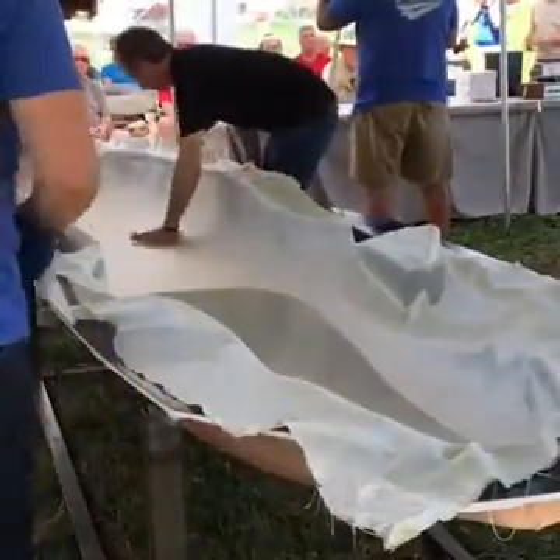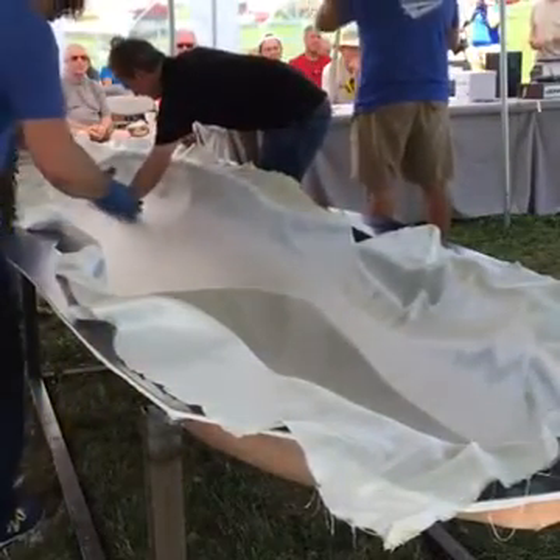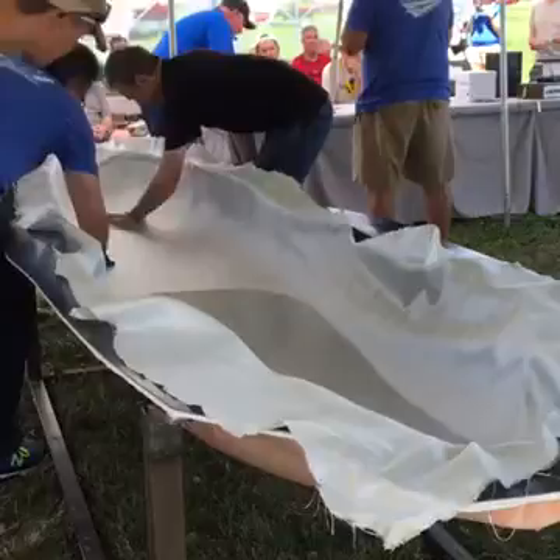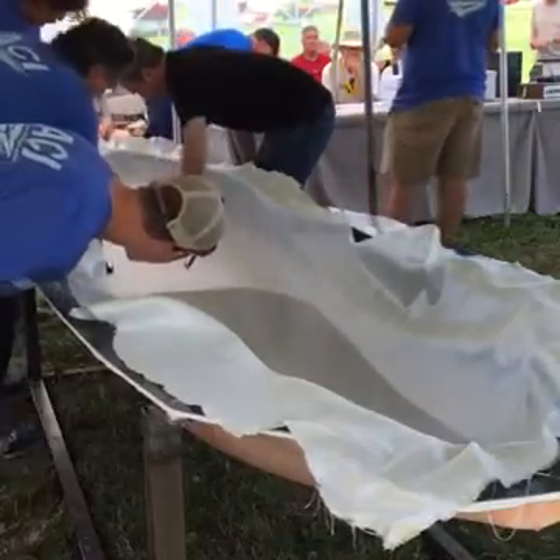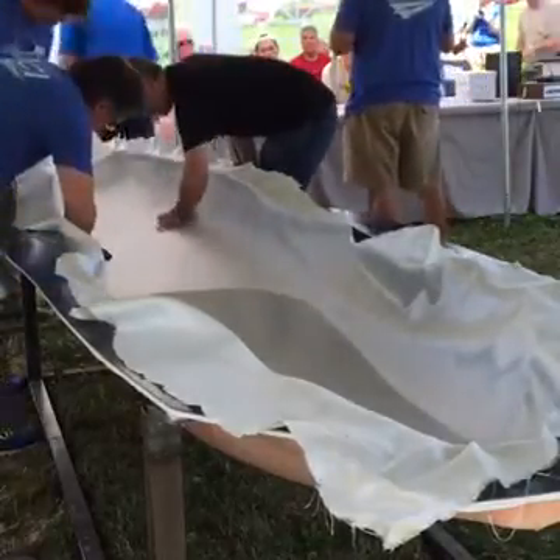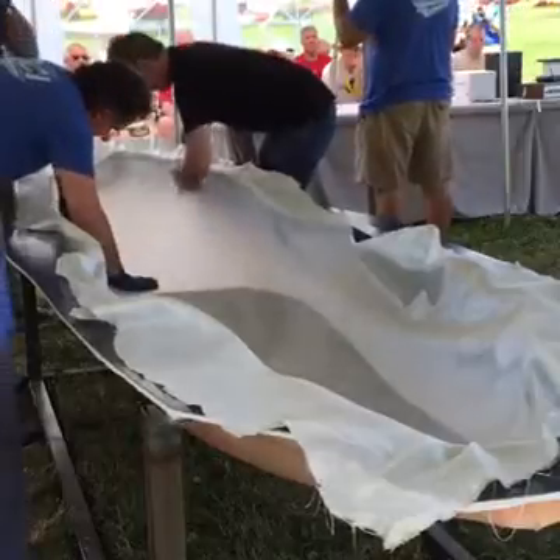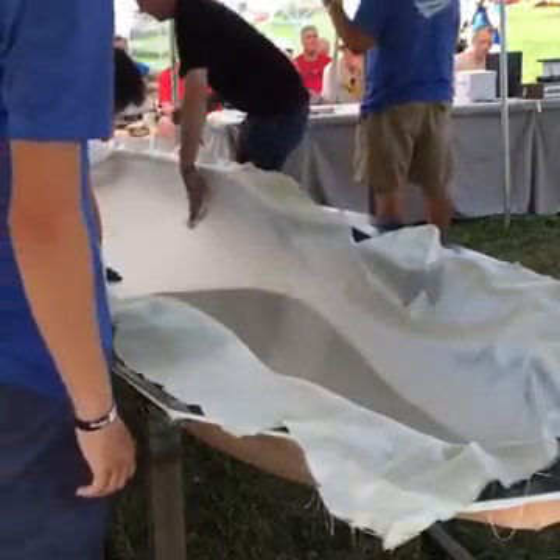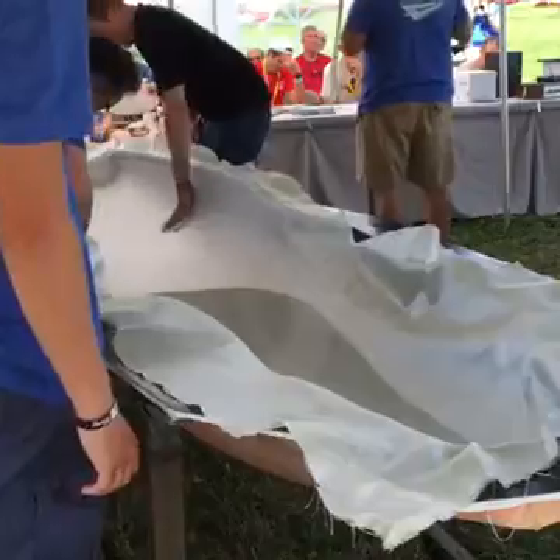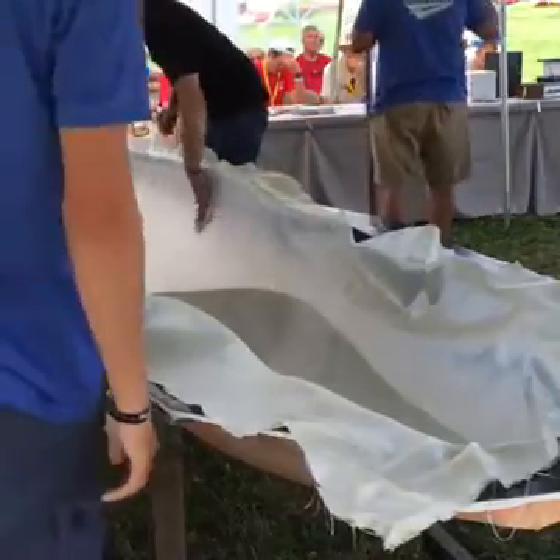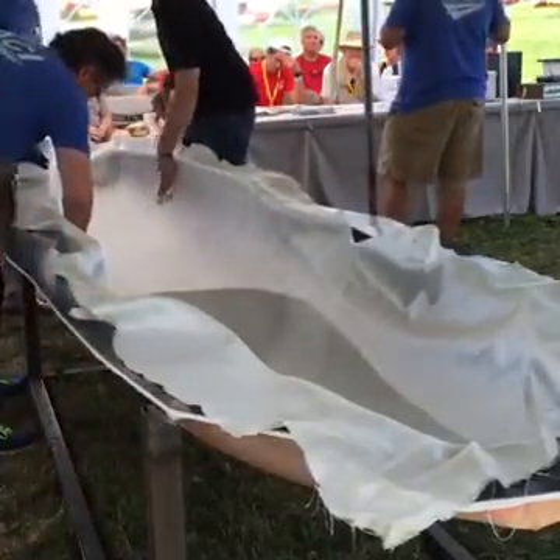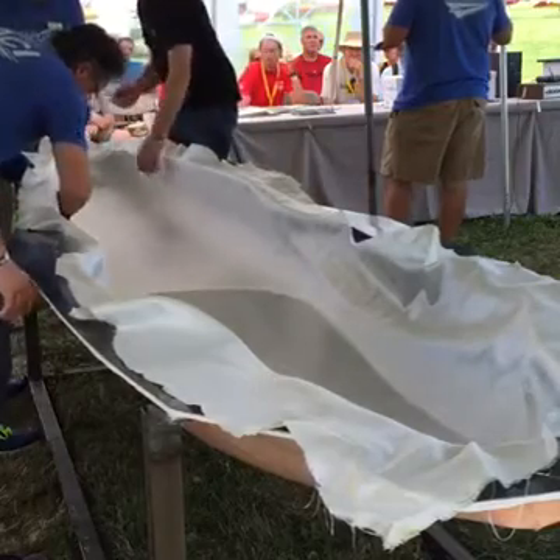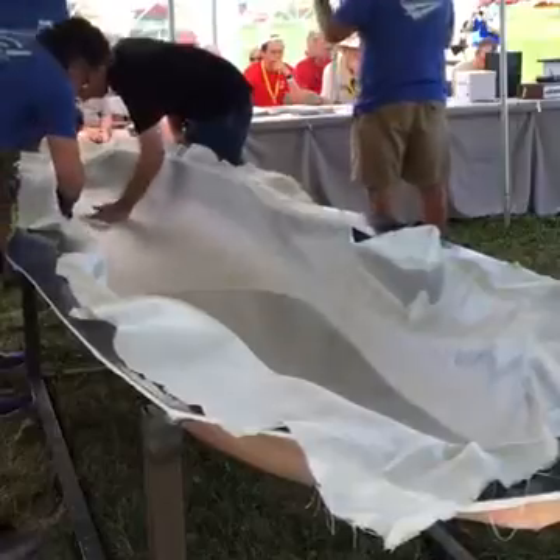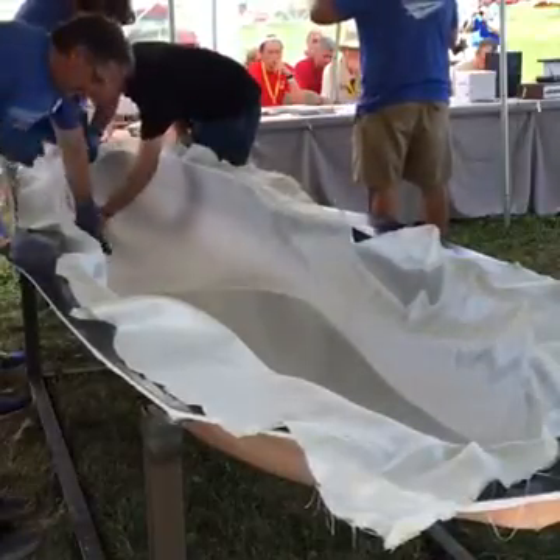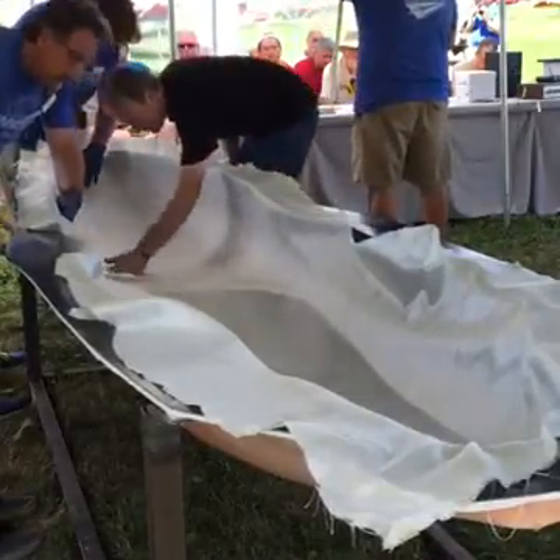When it goes to that second phase, it'll start getting very hot. The exotherm that we've measured usually is about 375 degrees Fahrenheit. So you're going to see a nice hot material. That's why I say you really don't need a post-cure. But any type of cure that you do, the glass transition is about 110 degrees centigrade, which is about 225 F. So it's going to get up to like 370 F post-cure all on its own. So it's going to be above its Tg.